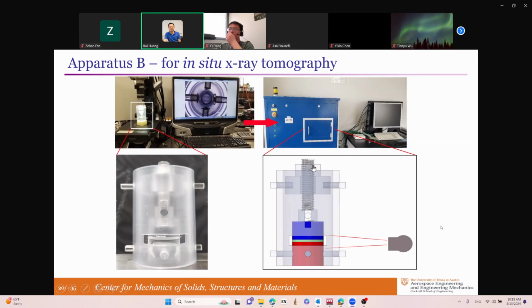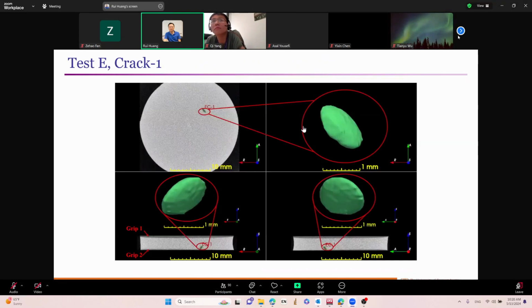So you would use a wrench to incrementally load the specimen, observing it inside an optical microscope. Stop the loading when we observe the first nucleation of the crack. Preserve the displacement constraints so the crack remains open, and put it in the bay of an X-ray tomography system and visualize where the crack is.